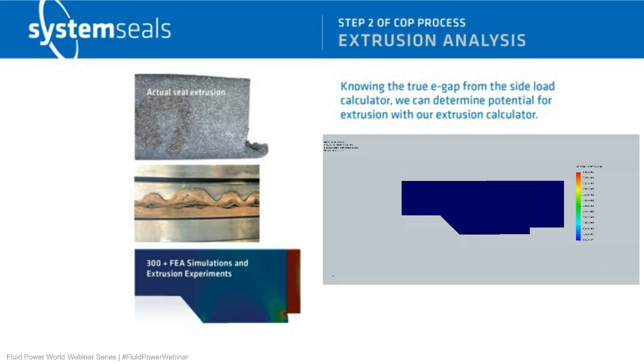So for example, in the upper left-hand corner, we see a profile of a rod seal that has experienced either a gap that was too large, a pressure that was too high, a temperature that was too high, or a material that perhaps wasn't strong enough to withstand the extrusion potential in the system, and so that material extruded into the E-gap. And you can imagine over time, as this little tail continues to grow, material may break off. This process continues indefinitely until eventually there's a catastrophic failure.